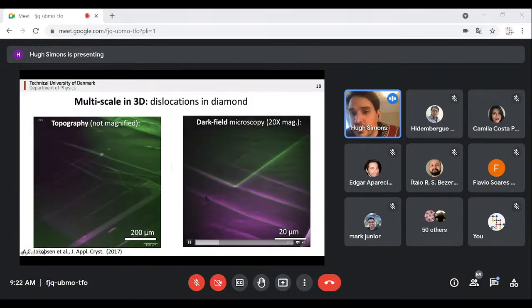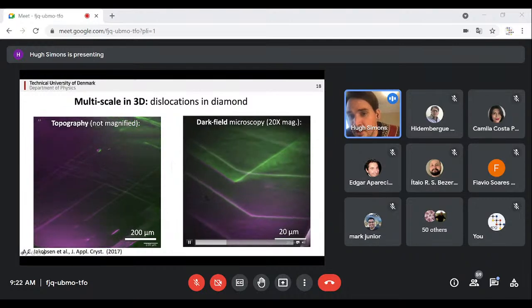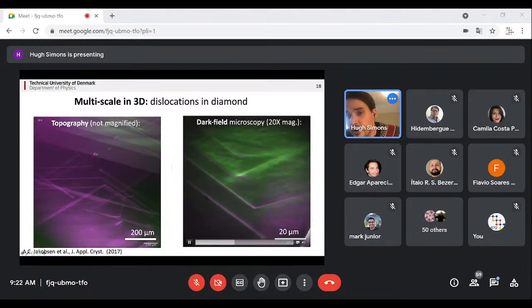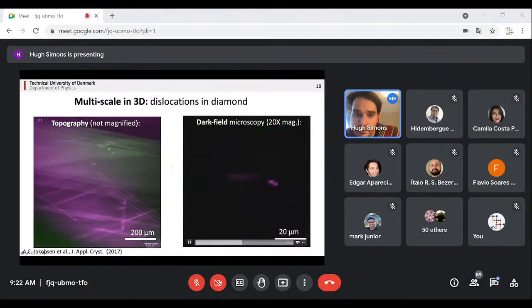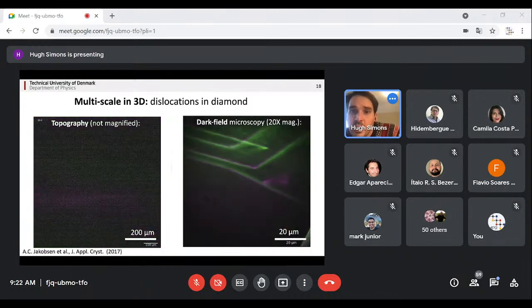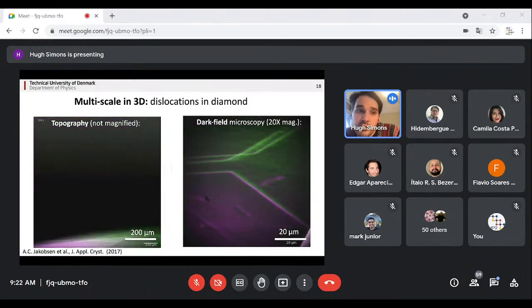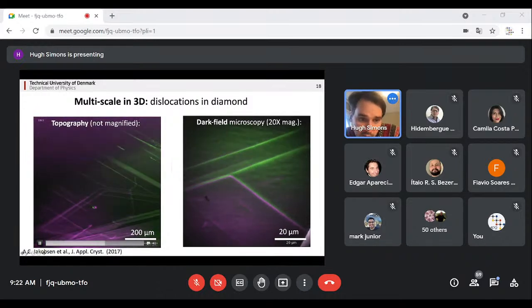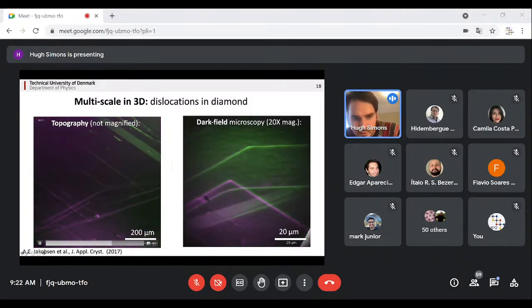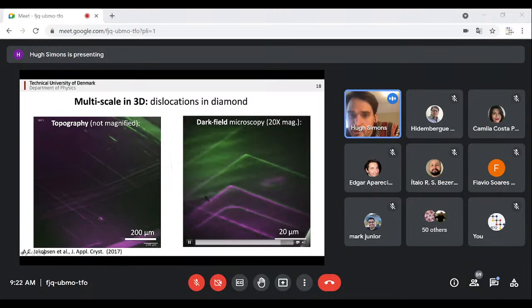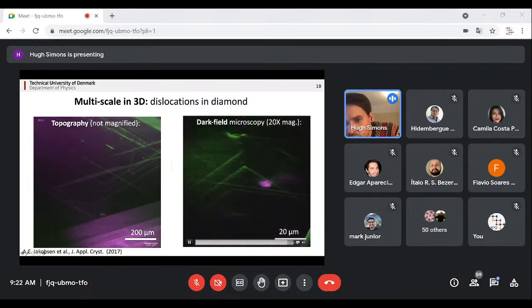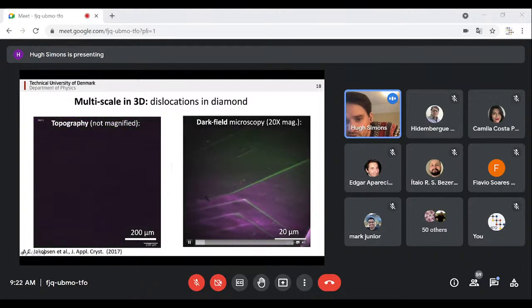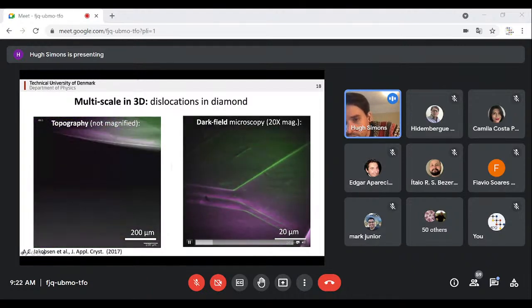And so what you can see here are individual dislocation lines inside diamonds as the sample is being rotated through 360 degrees. And by changing the magnification of the X-ray lens, we can see this both as the overall structure throughout the crystal and also in much greater detail. And as you zoom in, you can start to see finer features in the material, like, for example, this stacking fault in here.